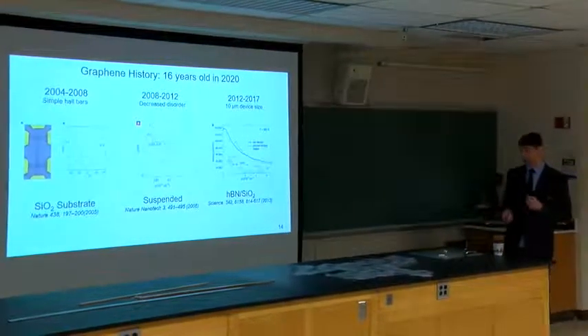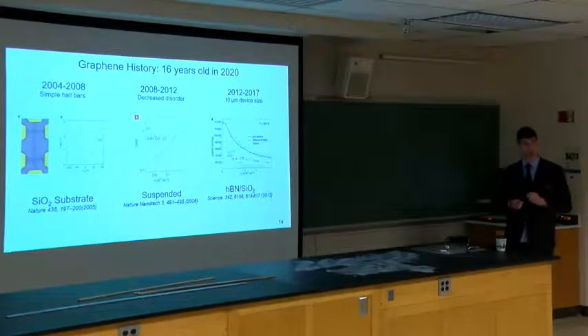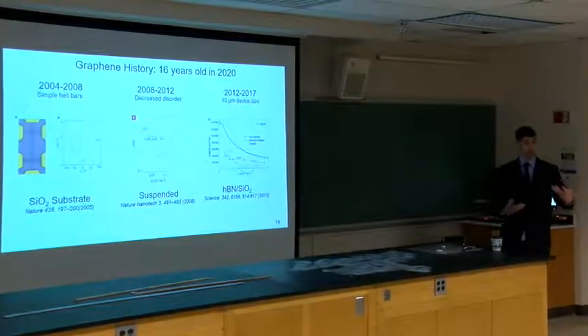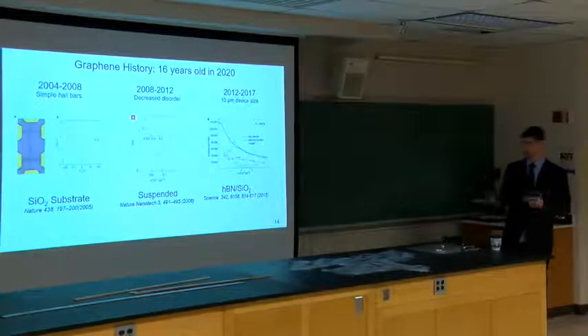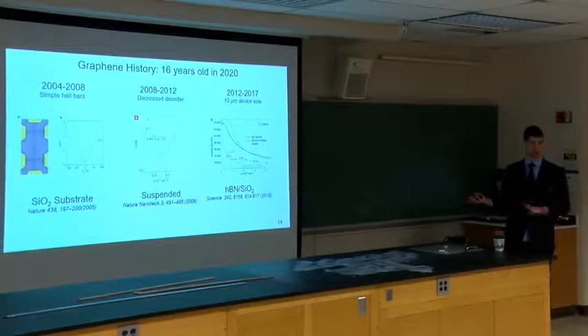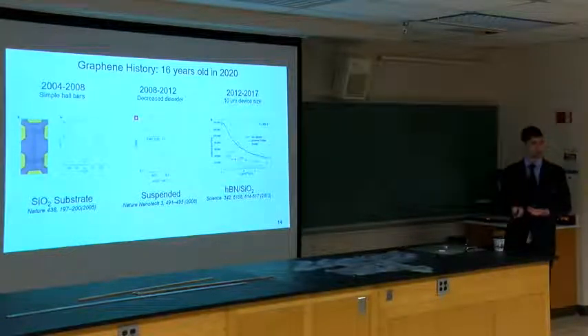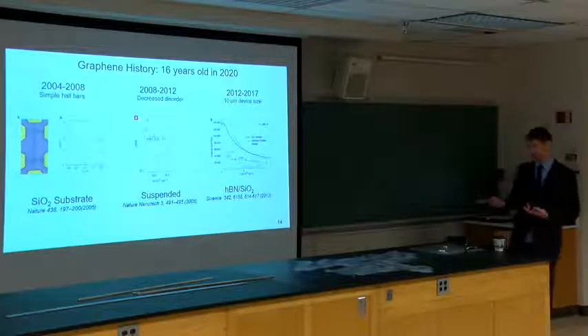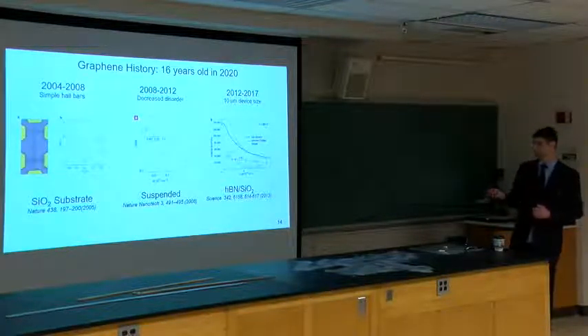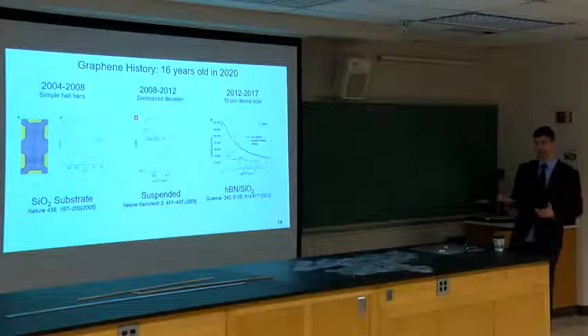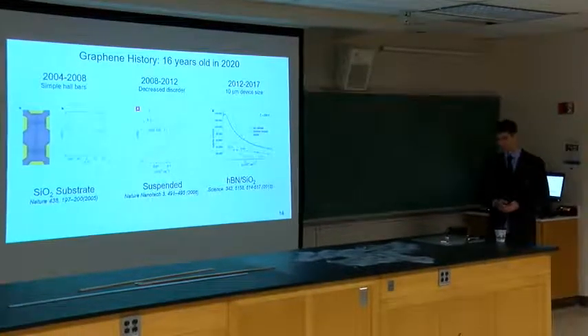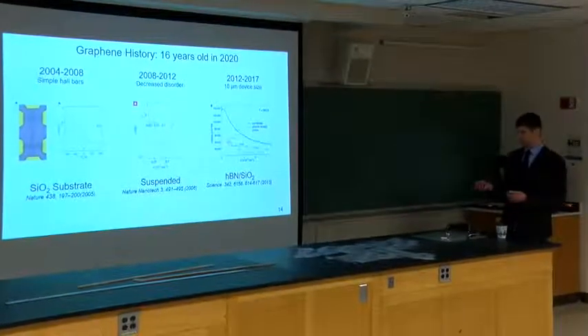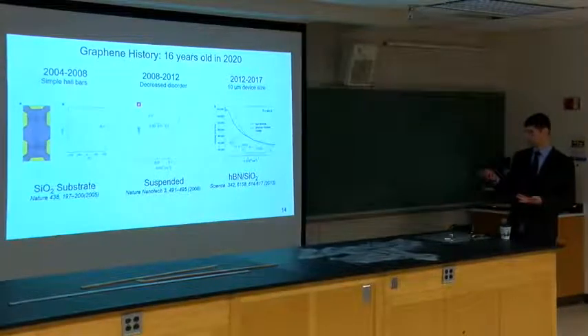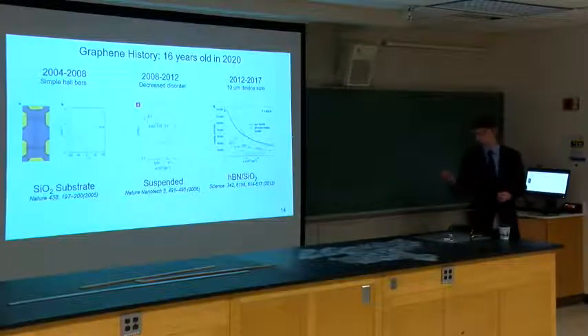You can actually get a very, very low residual charge density in the graphene because there's no defects around it, right? It's completely suspended. They're not very useful because suspending a single atomic layer of carbon is not only a nightmare, but it breaks. You're really limited on the amount of physics you can explore. Well, after HBN was rediscovered or discovered in 2011, 2012, we've been able to make much larger sizes, and